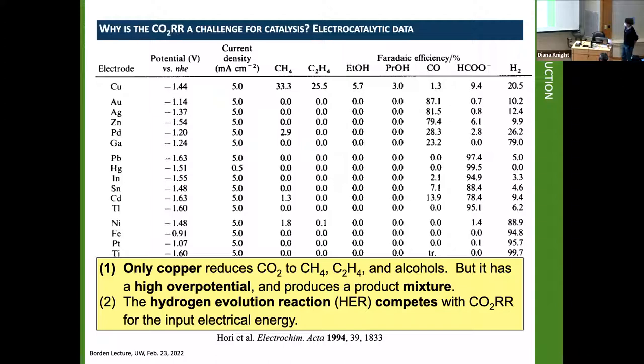If you look at ethene, copper is the only one that does anything significant. If you look at ethanol, copper is the only metal that does anything significant. Propanol, similarly. Many metals will reduce CO2 to CO, and you can do chemistry with CO if you combine it with hydrogen, Fischer-Tropsch type chemistry. But if you want to make hydrocarbons, copper is the simplest material that can actually do it, and virtually the only simple material that can do it. So hence, we will want to study in some detail why copper can do this.